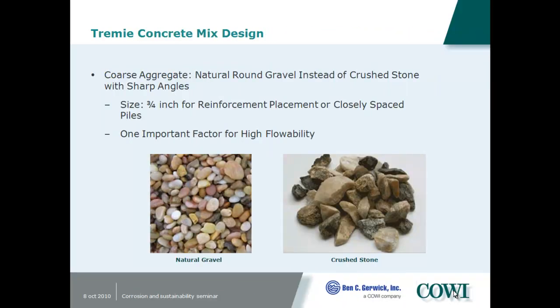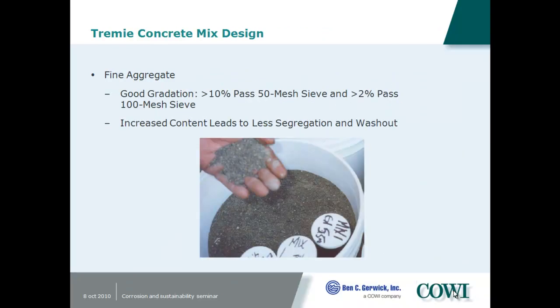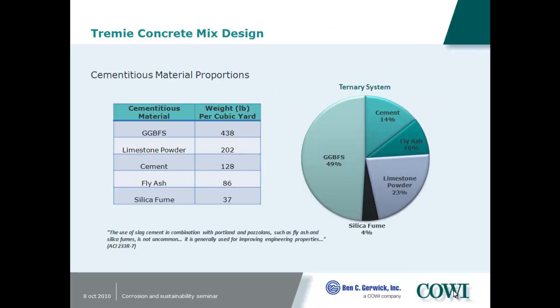So this is a photograph of the standard coarse aggregate. Just gives you an idea of the type of meshing we had. It's important when you do a mix design, you have to always observe the fundamentals. You shouldn't just use anti-washout admixture to solve your problems, or use a high-range water reducer to try to ensure workability. You have to have a good gradation of your aggregate to try to keep your cement content under control.